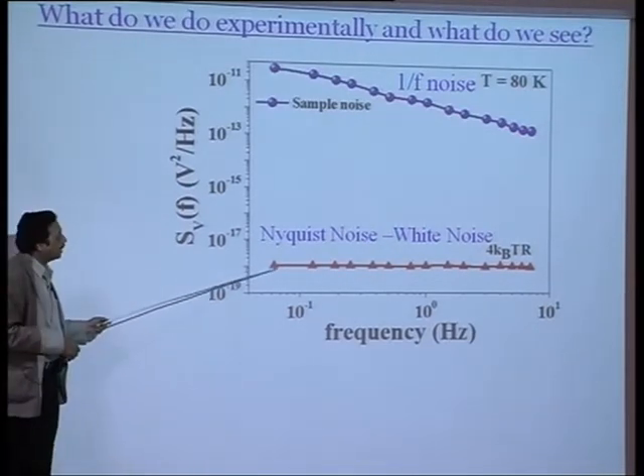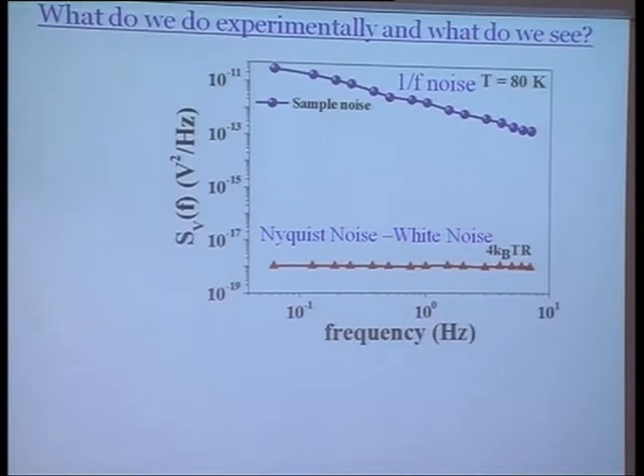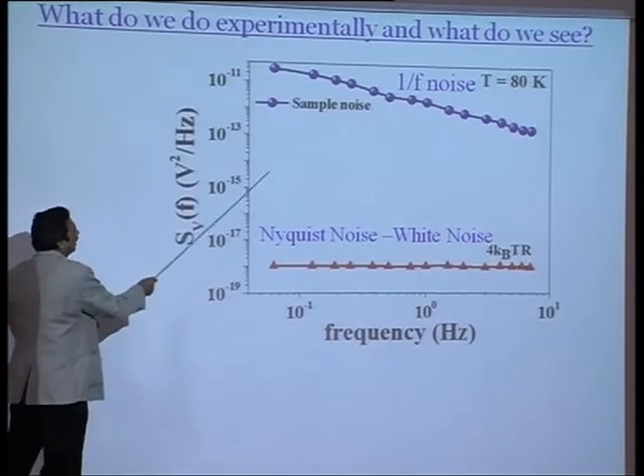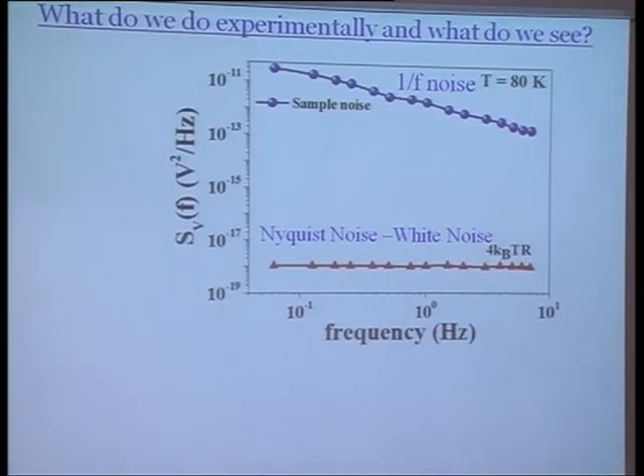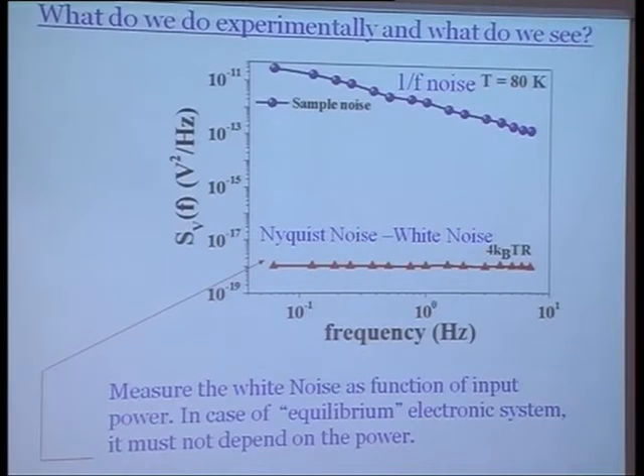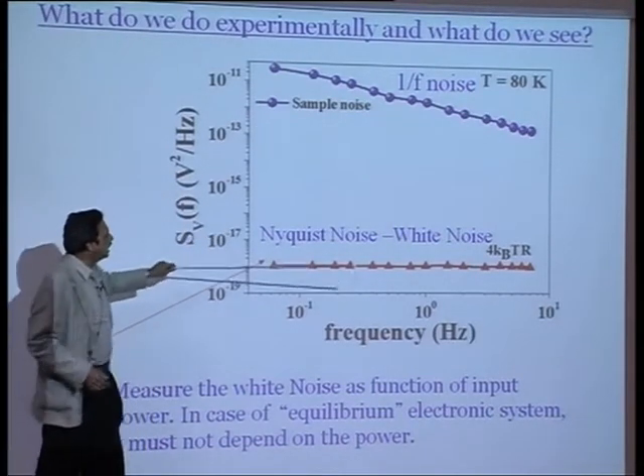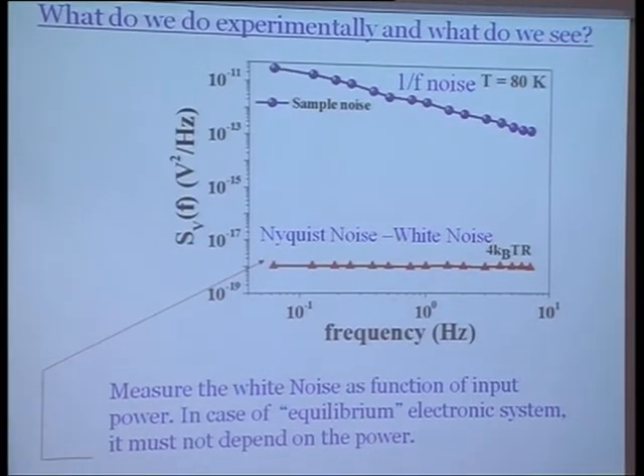Now, this is a very important number. Just to check whether your measurement is correct or not, you should always measure this noise. If your measurement is wrong, in the sense that you have a lot of extraneous noise, contact noise and everything, this won't sit at 4 kBTR, it will float somewhere over here. So we actually use it sometimes as a good diagnostic. Now, this is the measured white noise as a function of the input power. So why as a function of input power? For we know that if I change the input power, this noise should change, and the Nyquist noise doesn't change, as long as T_e, the electron temperature, does not change. So that is the thing that we try to look into.